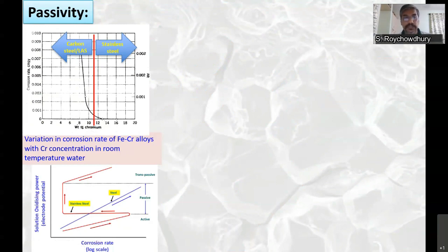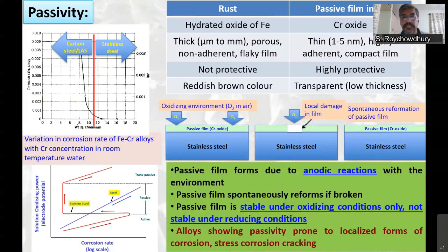So what is the reason for this? The main reason is the presence of this passive film, which is a chromium oxide, which forms due to exposure of stainless steel to the oxygen in air. It's highly adherent and highly protective as compared to rust. Rust is a non-adherent, flaky film. Of course, rust is also an oxide, but not adherent. The passive film is highly adherent, very thin, and highly protective. It cuts off the supply of environment to the base metal, reducing the corrosion rate. Because of its low thickness, it is transparent.